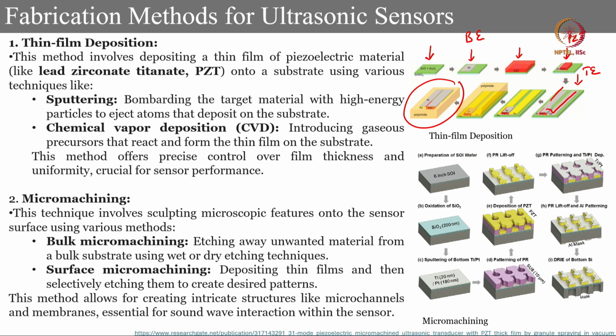Another way of doing it is by using the micromachining technique. You can start with an SOI wafer, then you can have oxidized silicon, with oxide growth using thermal oxidation, then you can deposit titanium and platinum. Titanium is used to improve the adhesion of platinum on the substrate. Then you can do a lift off technique, you can have PZT, followed by your top film, and you can pattern that, and then you can do a bottom DRIE silicon etch, so that you have your ultrasonic transducer.